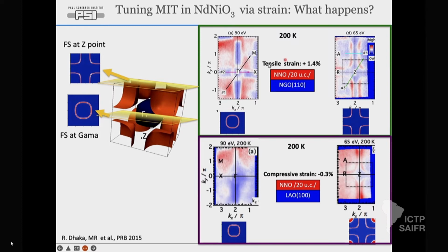We measured both films. Here you see the tensile strain film, measured at 90 electron volts. A good thing about having ARPES at a synchrotron is that you can choose the right photon energy to probe the Brillouin zone at the right position. So here it is the gamma point, and you can see these round things, which are a sign of the cuboid due to kz broadening, the spectral weight that leaks out because kz is not well defined. While at 65 eV, we are in the AZR plane, and you can see these cross-like Fermi surfaces. Everything that was calculated, we could see, so a very good agreement. This was done at 200 Kelvin, when the system is clearly metallic.